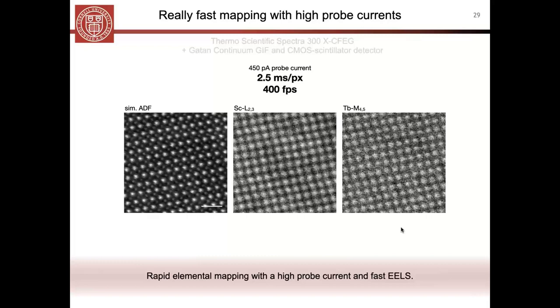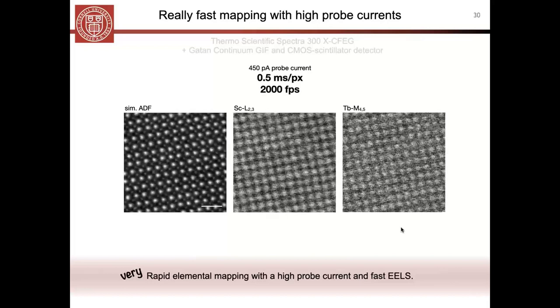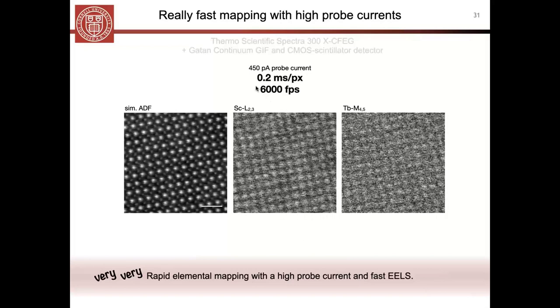And of course, using this high probe current, we can bump this even faster. We can drop that by a factor of 5. We're now running at 0.5 milliseconds per pixel, or 2000 frames per second, and still preserving very nice atomic resolution information in both maps. And if you want to really push the limits, we've now dropped the readout time by more than a factor of 10 from the cryogenic maps that I showed you earlier. And so we're running at 0.2 milliseconds per pixel.